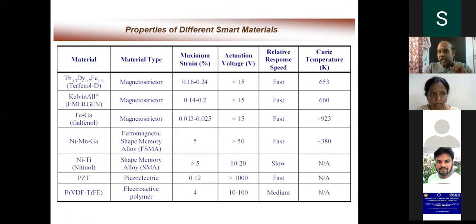The third one is nitinol. Nitinol also shows, because we have seen the wire, the twisted wire is going to untwist itself when you apply a thermal stimulus. But the problem here is that a thermal environment cannot be used all the time. And one more thing is the frequency response in this material is also difficult, because we cannot heat a material fast and cool the material fast. But in the case of a magnetostrictive material, you can apply an AC current at any high frequency, up to 1 kilohertz or up to several megahertz.